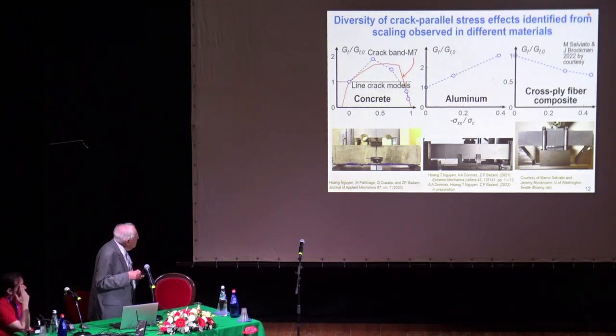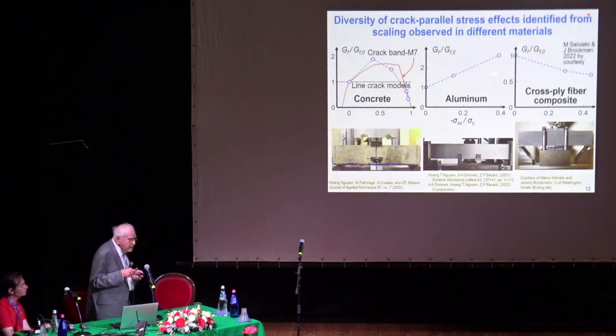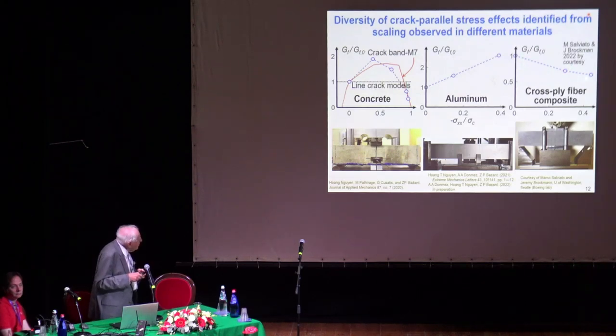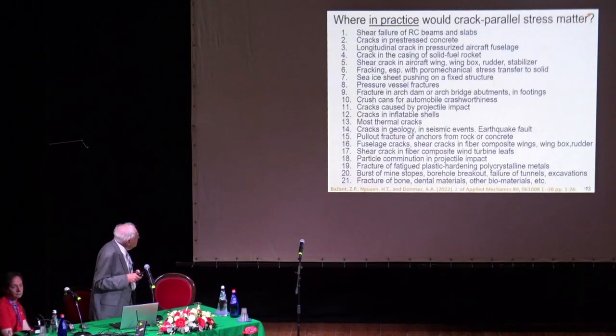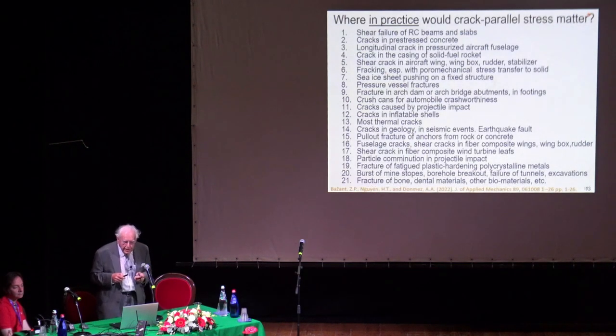The same test is shown here, with a picture of the test. When we tested aluminum, which was interesting, we are still doing that, you see the size effect in aluminum too. That was not studied before, and already at 40% crack-parallel stress, you increase the fracture energy 2.5 times. It's a major effect. My former postdoc, Professor Salviato, now in Seattle, working with Boeing, tests cross-ply fiber composites, and here at 40% of the compressive strength, you reduce the fracture energy almost to 1/2. These are major effects. These are some pictures from these experiments, which are still going on, and actually in several places. This phenomenon, crack-parallel stress, is ubiquitous. Almost all practical problems have significant crack-parallel stress.